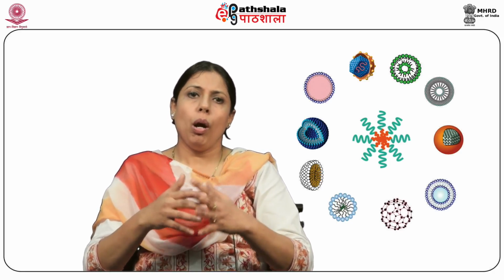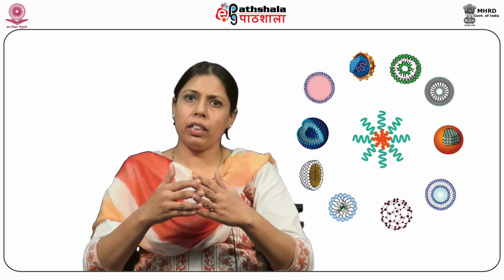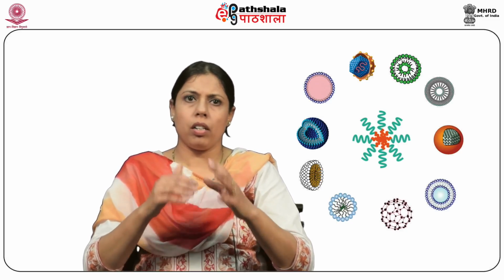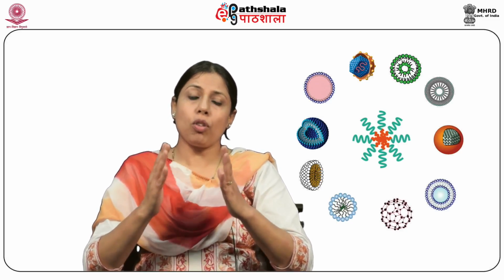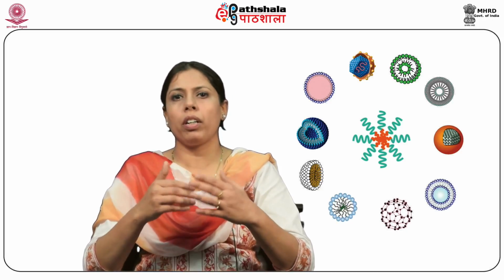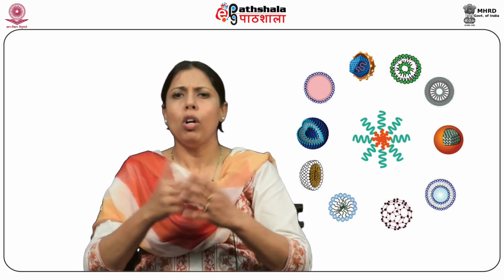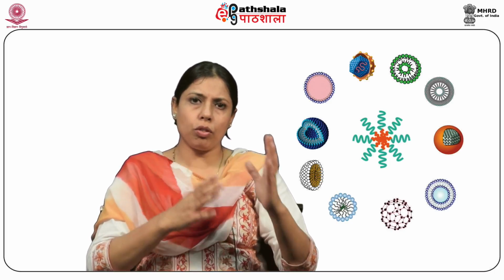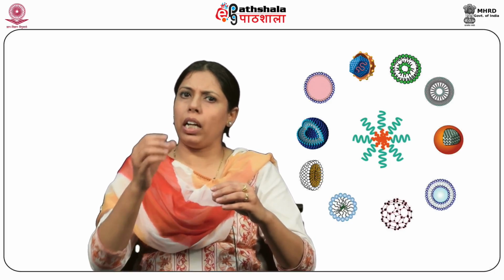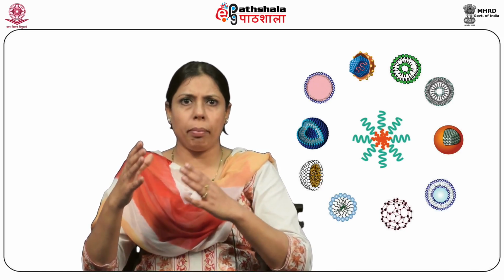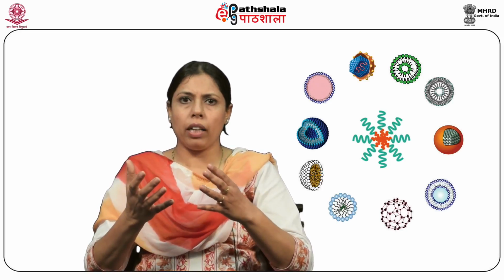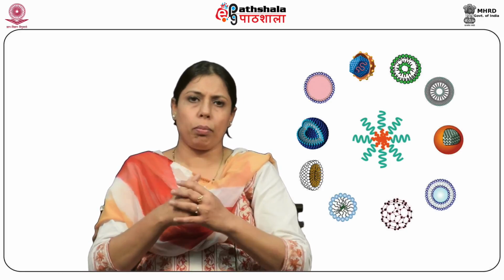So what we do is take a stock solution of surfactant like span 60 and add cholesterol to this stock solution, and this stock solution is made in a mixture containing chloroform and methanol, usually in a ratio 2:1. Now, from this stock solution, we separate out the aliquot in which all the components are present, and we add this aliquot to a round bottom flask containing the carrier, usually maltodextrin or sorbitol.